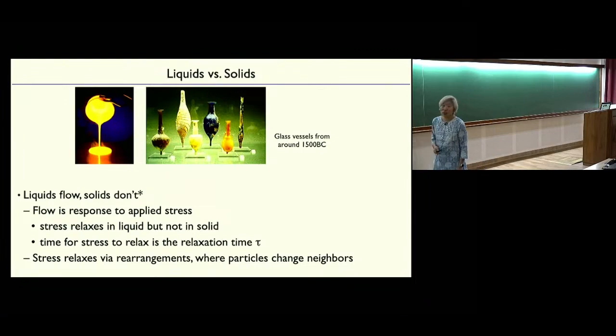Okay. So the big difference between liquids and solids is that liquids flow and solids don't, which means that when you apply a stress to the flow, it relaxes in the liquid, but not in the solid. And the time it takes for that stress to relax is what I'm going to call the relaxation time, tau alpha. Now, how does that stress relax? It relaxes by rearrangements, where particles change their neighbors. And that's what doesn't occur so often in a solid.